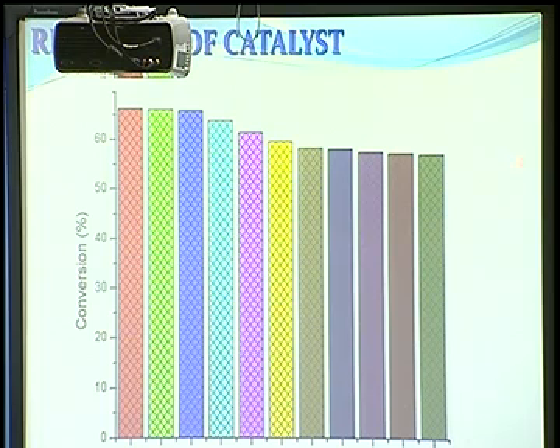Now recycling of catalyst, this is the beauty of my catalyst. It can be recycled for 10 times without significant loss. In first cycle it has 66.19% conversion, which decreases to 56% in the 10th cycle, which is not so much of difference, and it is the beauty of heterogeneous catalyst also.